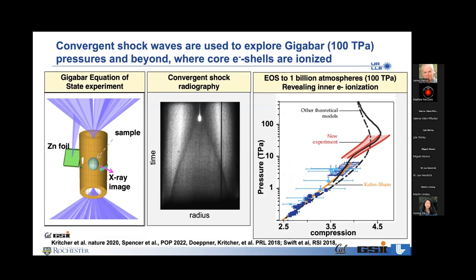And this shows one experiment that we did. We took a ball and put it in the center of one of these gold cans that I showed earlier, and we launched the compression wave, just a single shot. We took a snapshot. So we took a zinc foil and hit it with other laser beams that produced X-rays that shine through this ball. It allowed us to follow the shock wave. The shock wave moves through this ball. And then we mapped the velocity and the density that gave us the mechanical states, pressure,